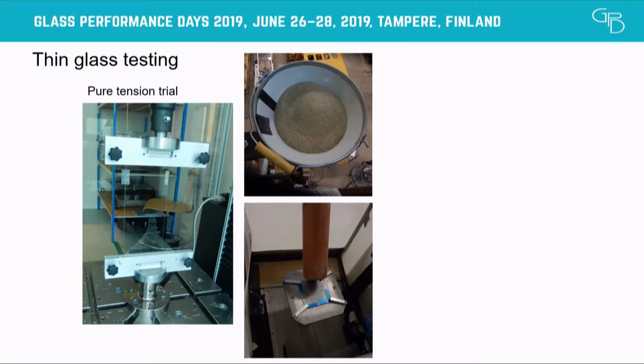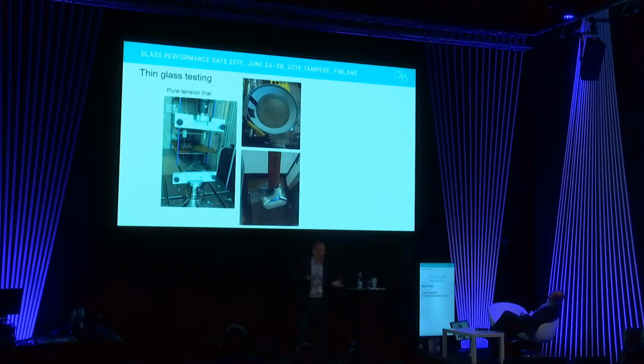But luckily, out of 30 specimens, apparently it was well designed, 25 break from the center. I guess it's a good percentage if you even compare a normal 4-point bending where fractures sometimes even occur out of your loading span. And so this, for me, is a new way of testing. I'm testing chemically tempered, non-chemically tempered, and different edge conditions to see what's the real strength. Data are still in analysis for this sort of test. As I'm talking, I know the technicians are doing tests on it.